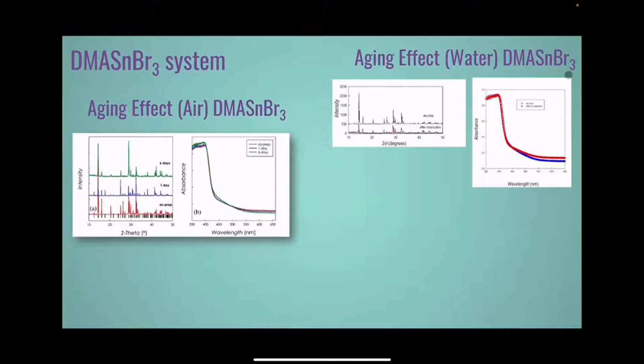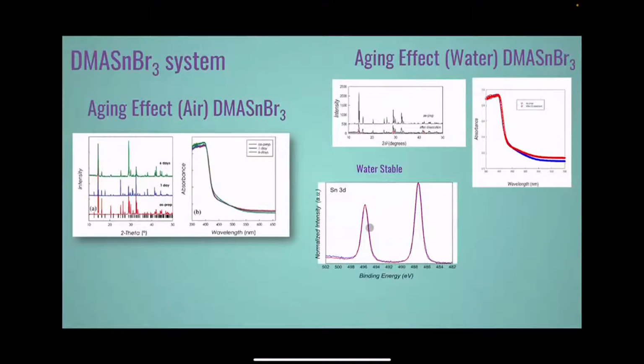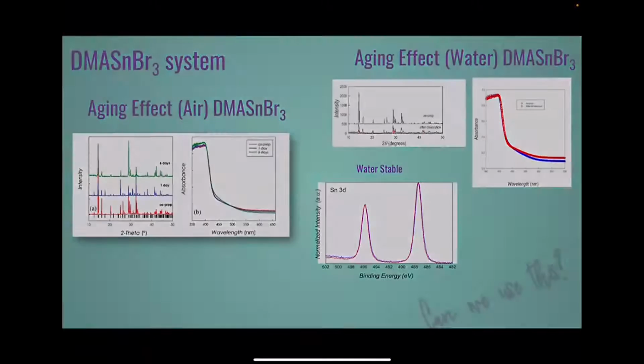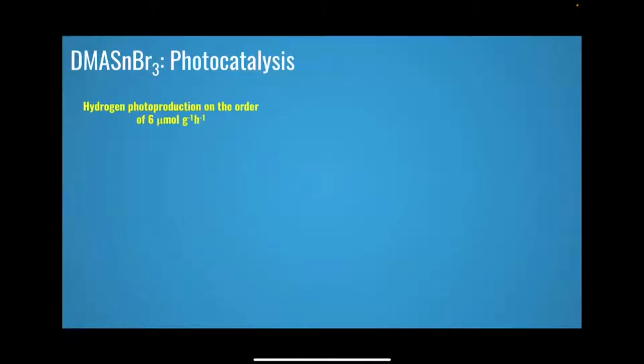To be honest, in those months when we discovered this behavior, another group observed the same behavior on the iodide analog. Also in the XPS, look, the tin 3d position of the peaks of the as prepared material and after water didn't change. Tin remained tin 2+. So in some way, we thought that this dimethylammonium cation could protect the tin from oxidation, and in general perovskites from water sensitivity. So the idea was how we can use this. Our idea was initially to try to develop hydrophobic metal perovskites. The first test we did was to try to use it as a photocatalyst.